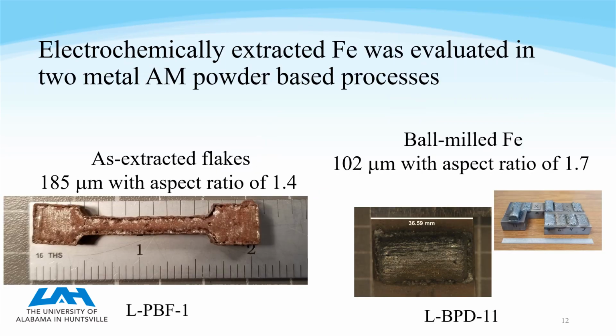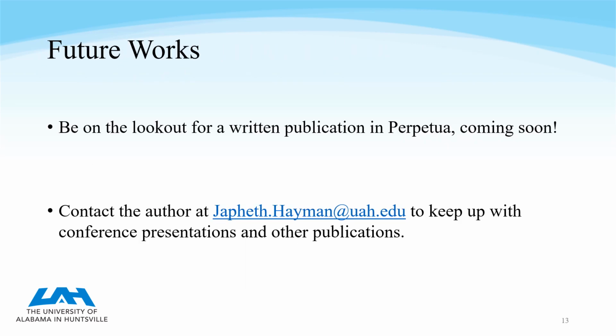So we took our two flake-shaped powders and tested them in the additive processes that we were looking at. So we used the raw as extracted flakes, the bigger ones, in powder bed fusion, and then we took the ball milled flakes and tested those in blown powder deposition. Now we have at this point done some testing on both of those builds, but that is beyond the scope of the summer research. To hear about that testing that we've done, be on the lookout for the write-up, which will be in Perpetua, our UAH undergraduate research journal, hopefully this fall semester. If not, then definitely in spring of 21.